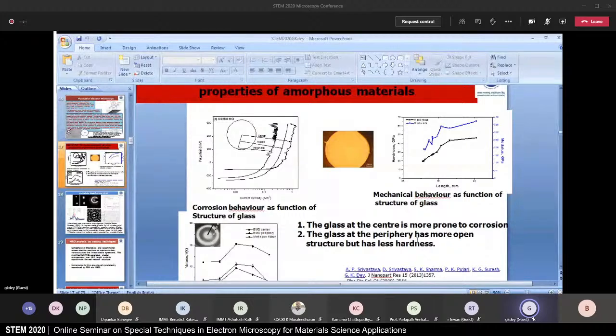So we have used both the modes of electron microscopy, and actually we observed in the glass, this glass here, that the central region has higher nano hardness, and as you go to the periphery, you have lower hardness. Similarly, we observed that this region has poorer corrosion resistance. As you go towards the periphery, it has better corrosion resistance. Everything is glass. Everything has the same composition. Then why this variation in properties?